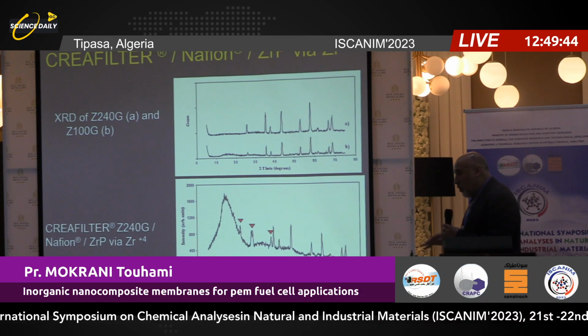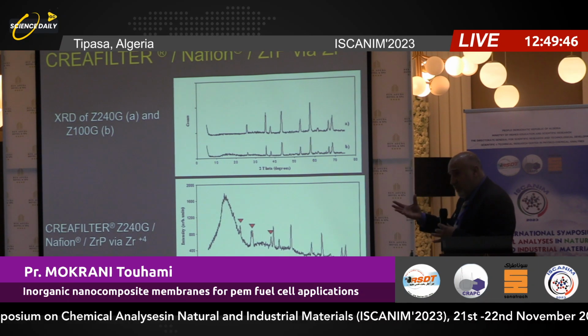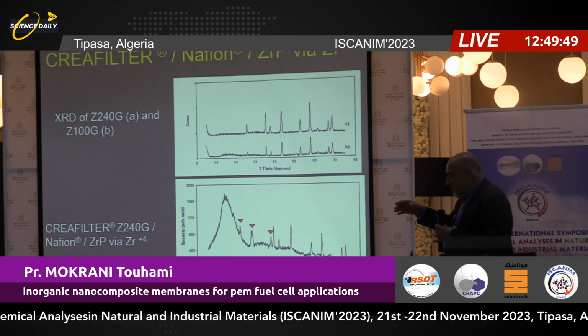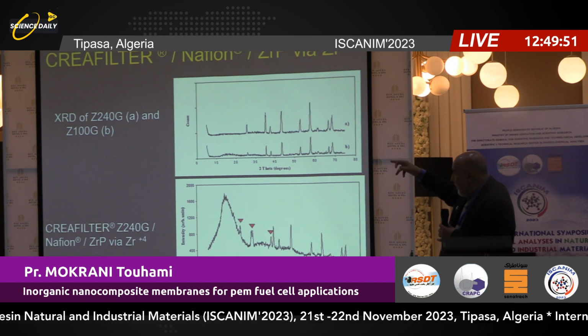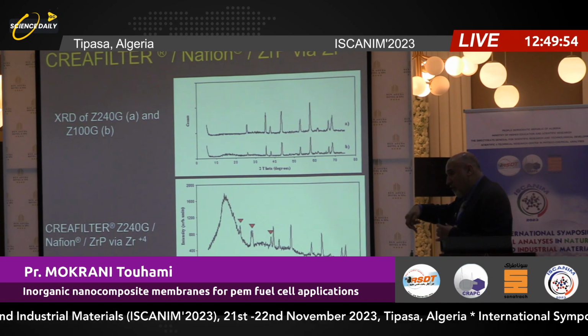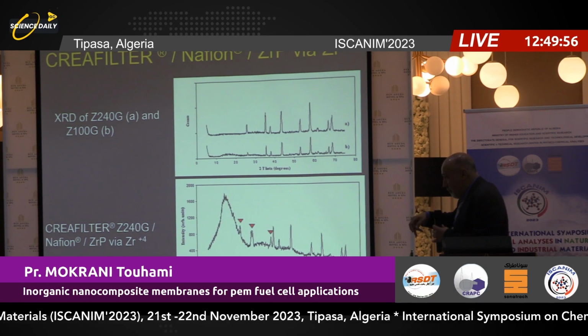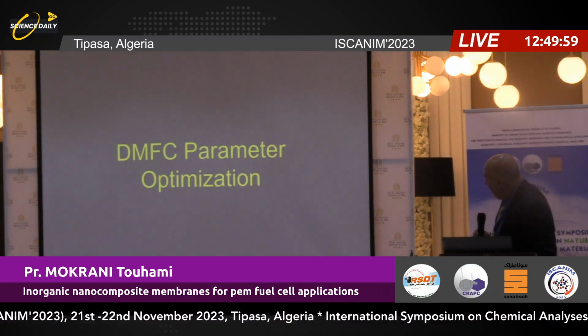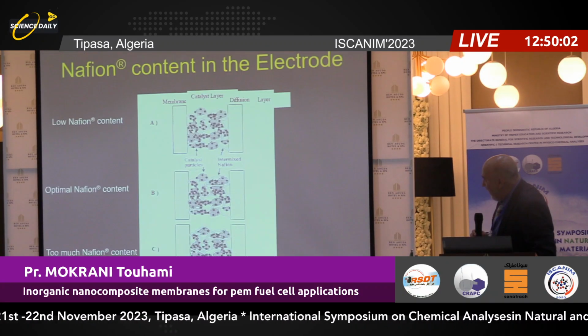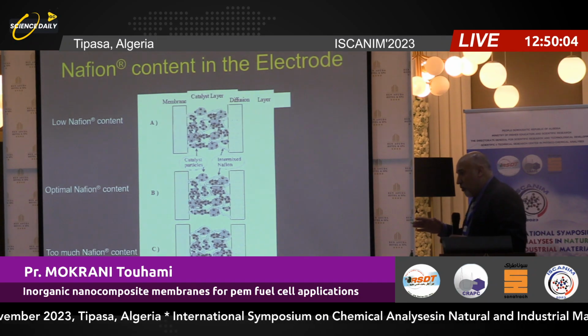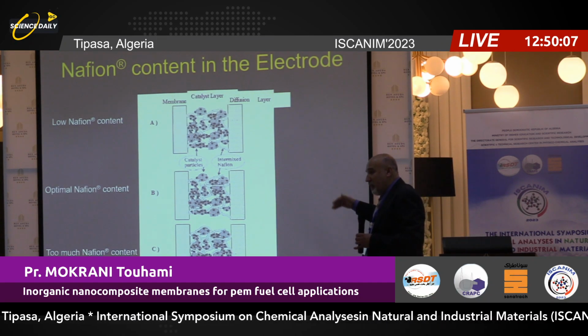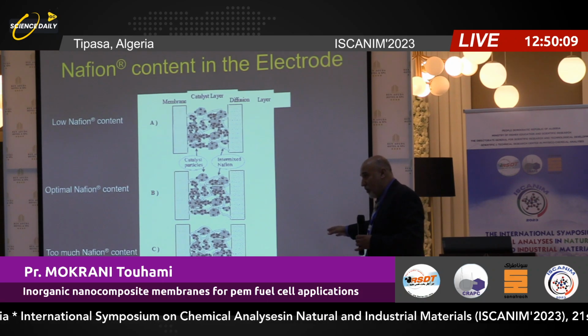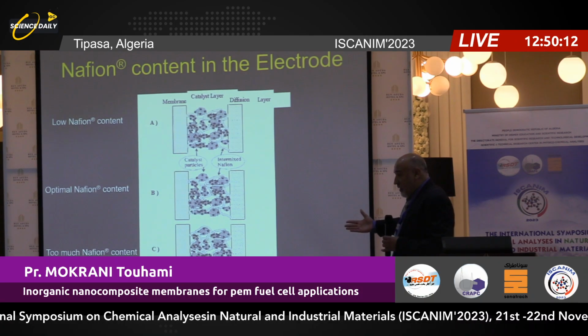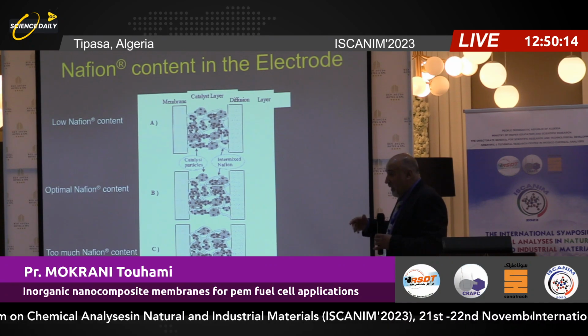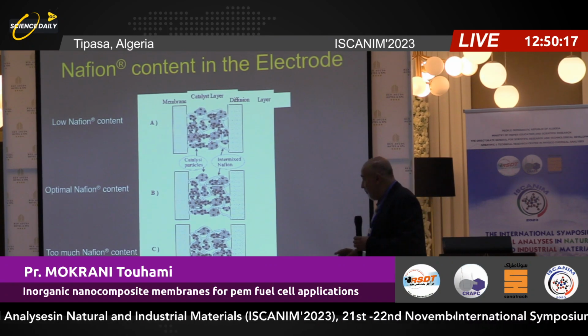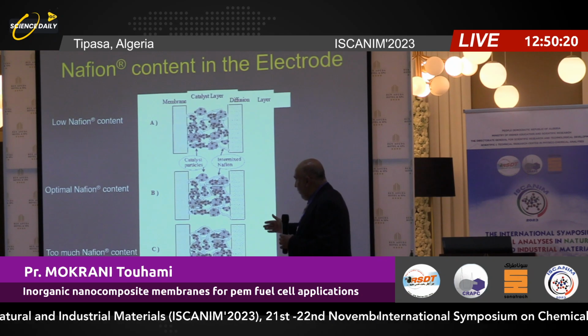So here we did the composite twice. First we take the inorganic material, the matrix, we put Nafion, and then inside the Nafion we impregnate it via ion exchange with zirconium phosphate. Here is DMFC performance. All the time I am saying the selectivity is better than Nafion. So it's supposed to perform better than Nafion in a real fuel cell, which is not the case. Because one of the things about the fuel cell,